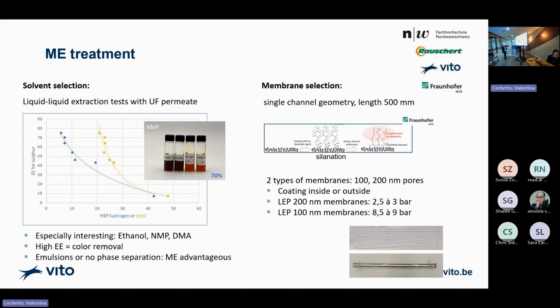Now, we picked out, it's also nice to see the efficiency is quite good. We also have nice color removal. So you see back the brown color, what you wanted to have of the base oil. Now, we picked out especially 3 of them, ethanol, NMP, DMA, dimethylacetamide it stands for, and these have good extraction efficiency. Anyway, in all these cases, we had a lot of emulsions formed, a lot of phase difficulties to get phases out.